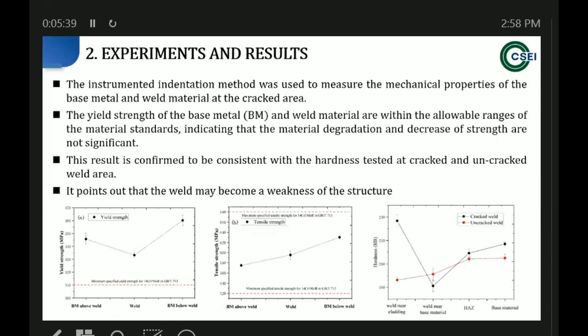We also used the instrumented indentation method to measure the mechanical properties, and we can see in this case the base metal had slightly higher strength than the weld material, and this is consistent with the hardness test. So we can see there's some weakness in the weld structure.